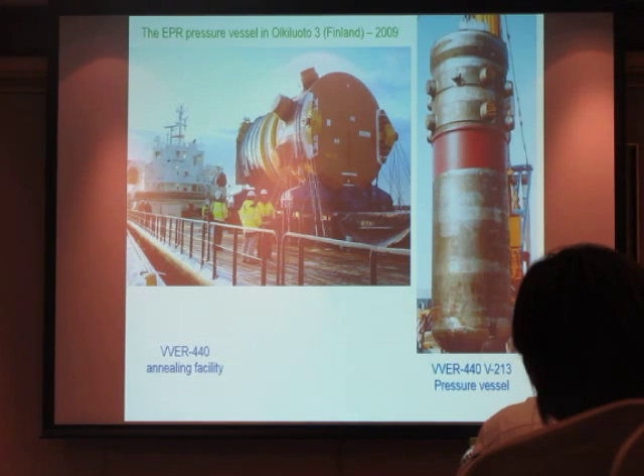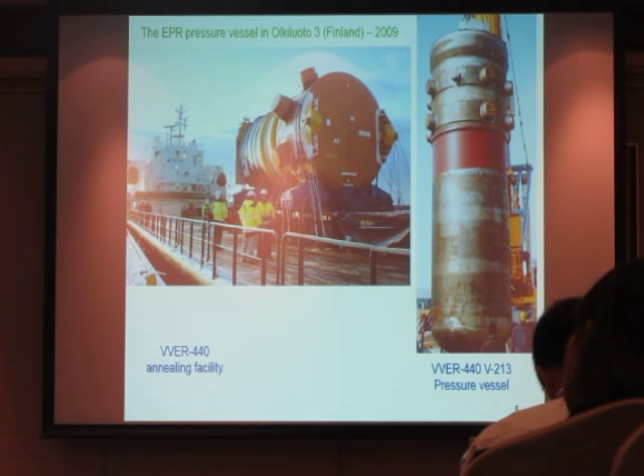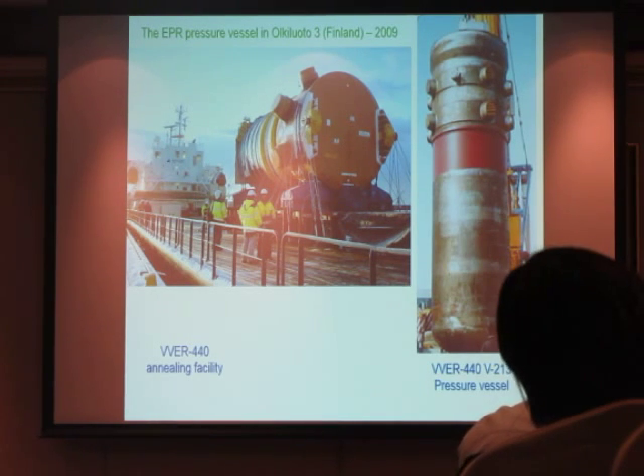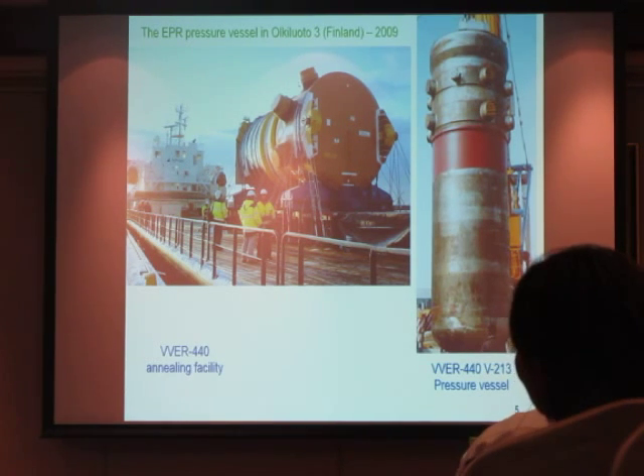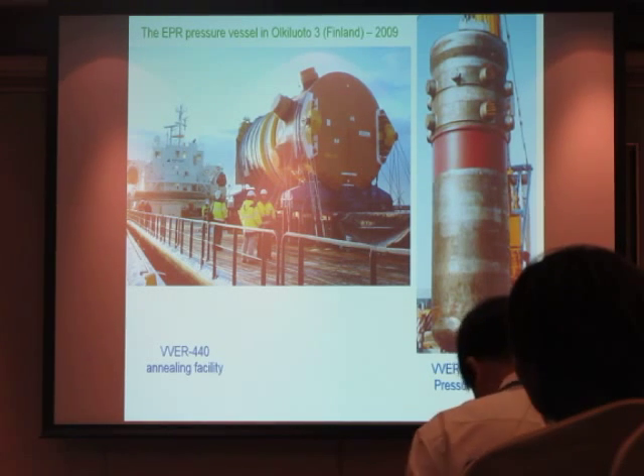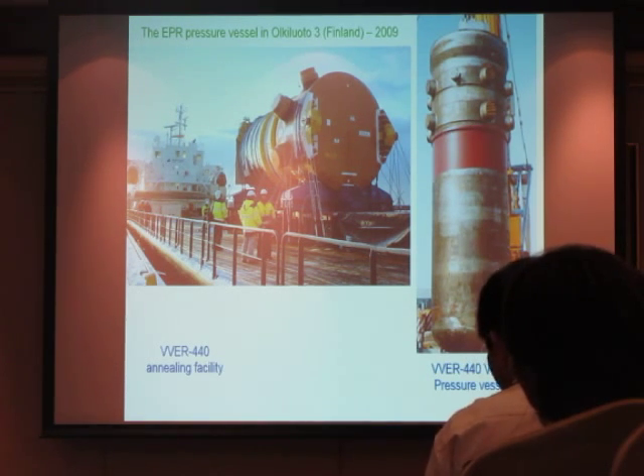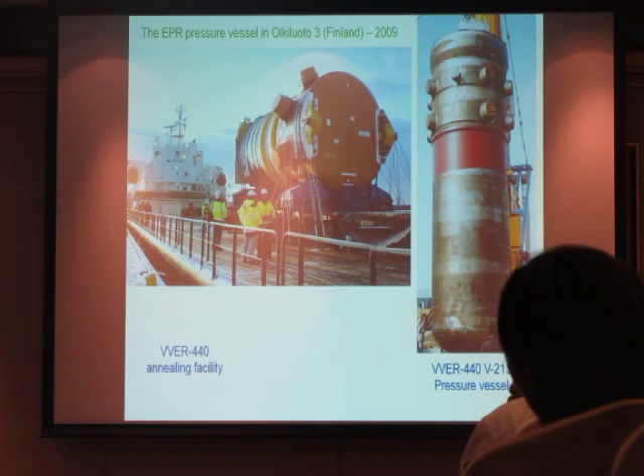Mr. Nagai said yesterday that the lifetime is limited to 40, actually 60 years, but each utility tries to prolong the lifetime. And it's necessary to prove that the reactor pressure vessel is okay. How can we prove it? Only to study the specimens, original specimens taken from the reactor pressure vessel. But if you take it from the wall, you cannot operate because it's damaged. So therefore, several specimens are put into the reactor, irradiated, and the study is performed on these several specimens.